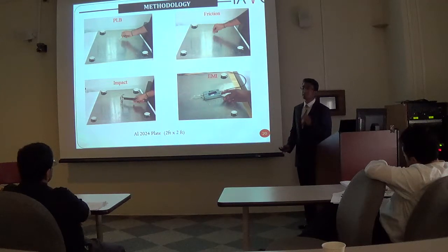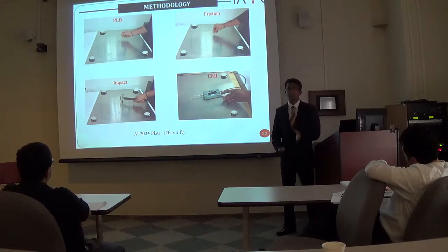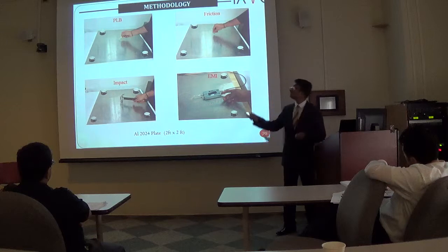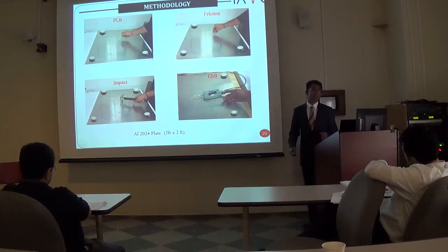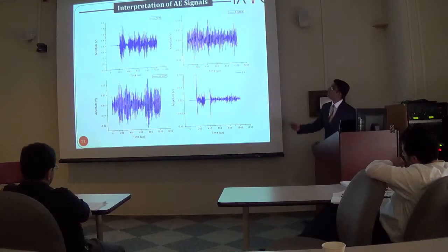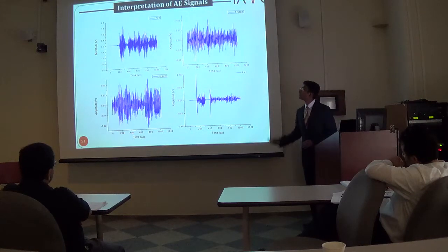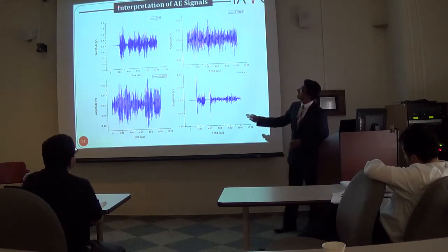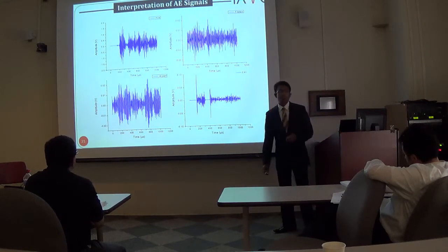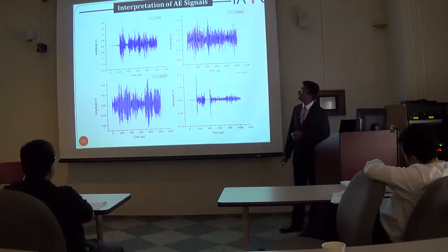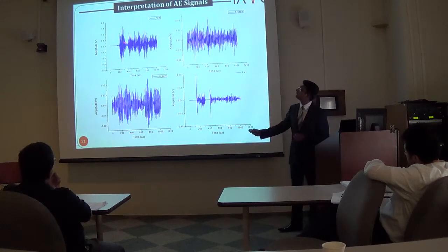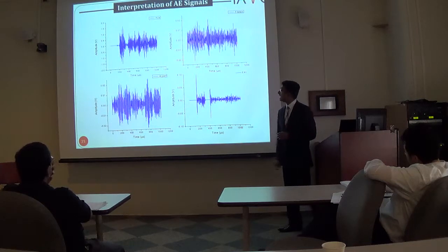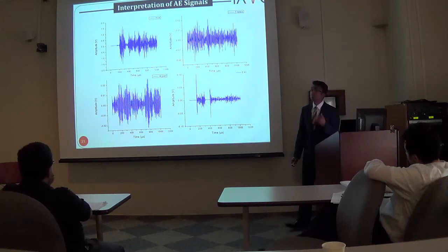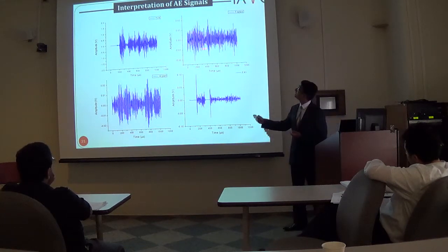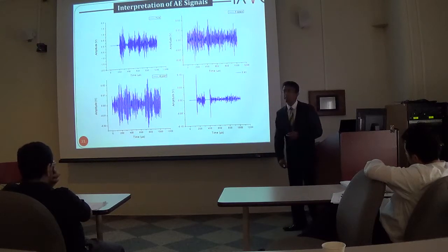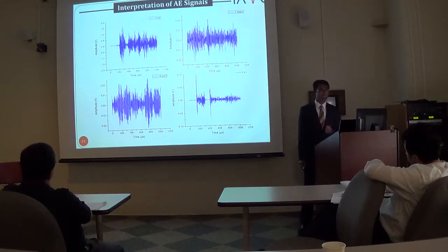And the goal here is to see if the advanced frequency analysis or the advanced feature analysis has the potential of separating these known AE sources in the test. The extracted AE waveforms from the four sources are shown here. Clearly, you can see that the PLB waveform had the highest AE amplitude in the test. But more importantly, it can be seen that the PLB waveform and the EMI waveform have a burst type emission, while the friction and the impact waveforms have a continuous type emission.